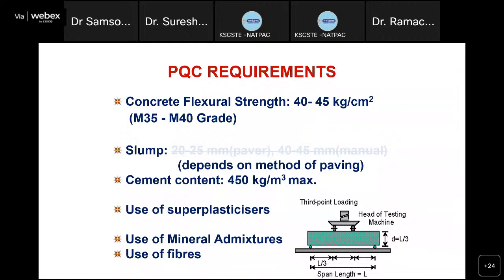For example, even with 360 to 370 kgs of cement, it is possible to achieve a strength of M40 concrete, 40 MPa compressive strength concrete. It is possible to achieve. We need to use super plasticizers, because when you reduce the water ratio and want higher workability, you need to use super plasticizer. And the use of mineral admixtures like fly ash or GGBS is also essential. They also improve the workability of concrete. But there is always a limit as per IRC. You can use only about 20 to 25% of fly ash in cement.